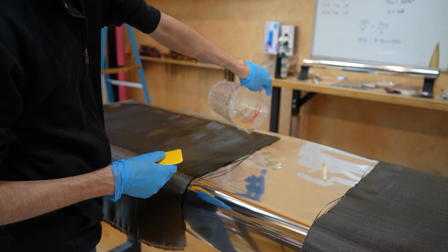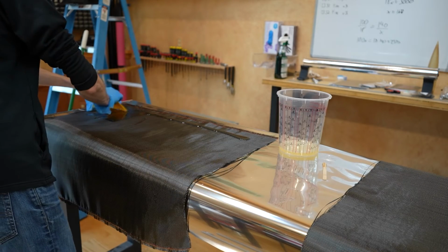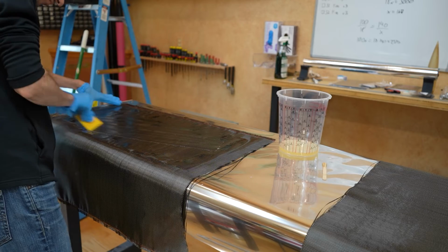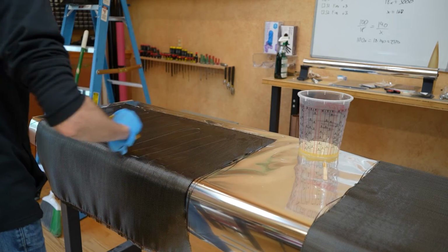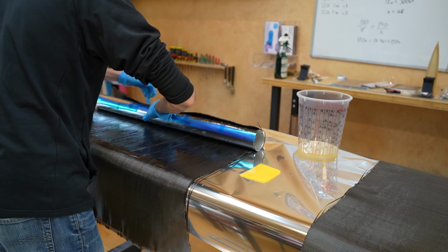I squeegee the resin into the fiber while it's laying on the table. This is a much easier shape and form factor to work with. Then, I roll the tube across the fiber on the table to get a tight wrap.